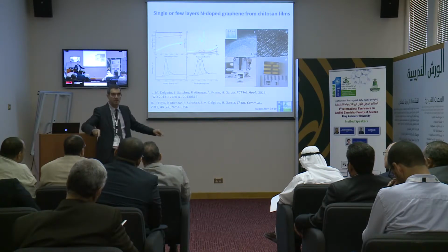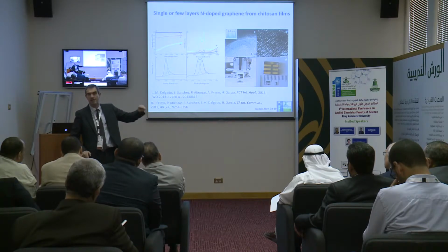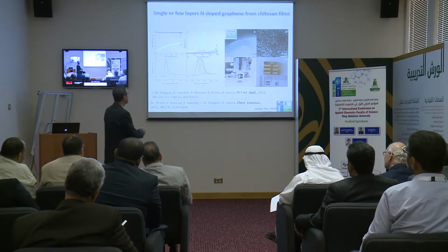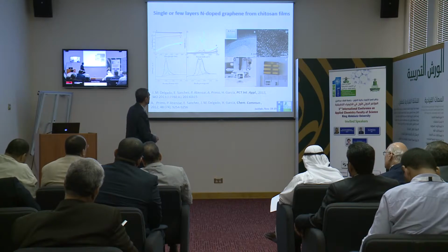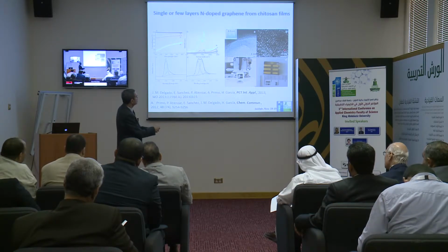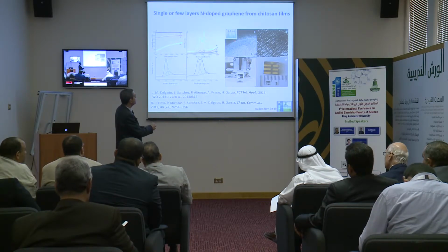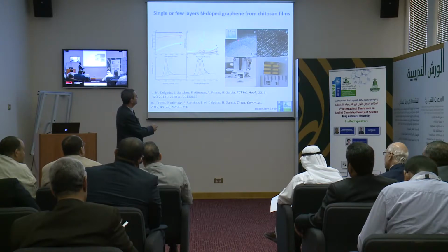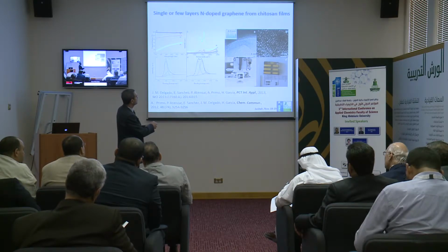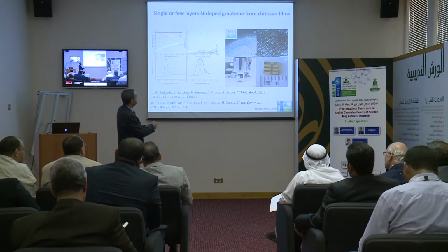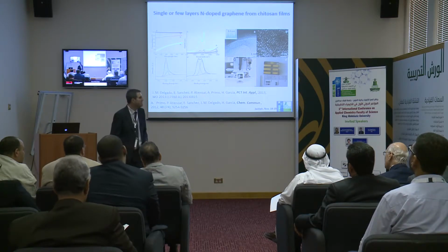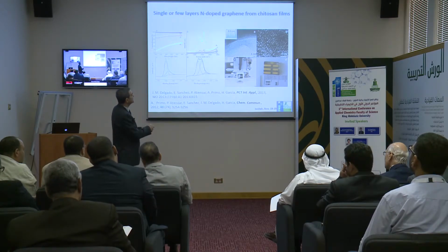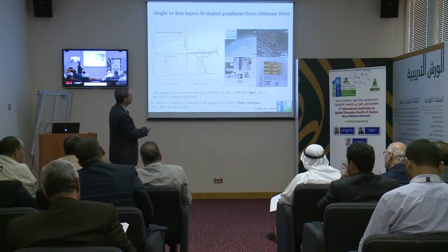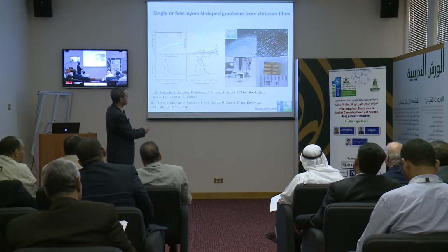So just in the border we have some nitrogens, and the borders there are not fully saturated, and this is the pyridinic nitrogen. And this is again the electron microscopy images, so we can count how many layers we have in this sample, and you can also, by contrast, count here the separation between the layers, that is always 0.34. And an expansion with high resolution shows that all the atoms are aligned, so we have something that is very well crystallized.